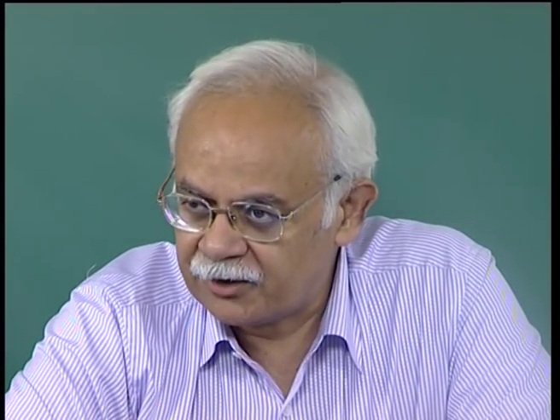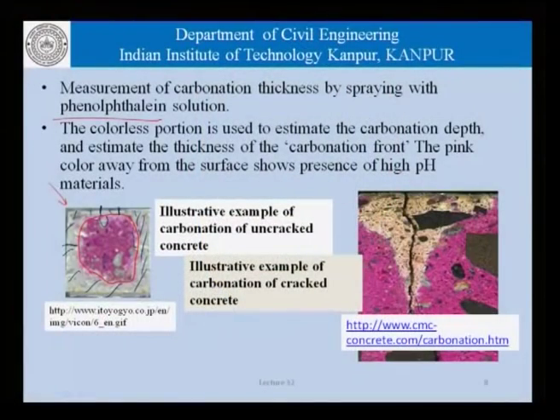This here is an example of carbonation as will occur in cracked concrete. What is being seen here is that in addition to the carbonation which has taken place in this part, which is let us say A, which is similar to this kind of an area where carbon dioxide has generally penetrated into the cover concrete. In addition to this, carbonation has also spread in this portion, let us say call it B, because carbon dioxide has gone through this crack and spread into concrete through the crack, causing the calcium hydroxide in the neighborhood of cracks also to be consumed.